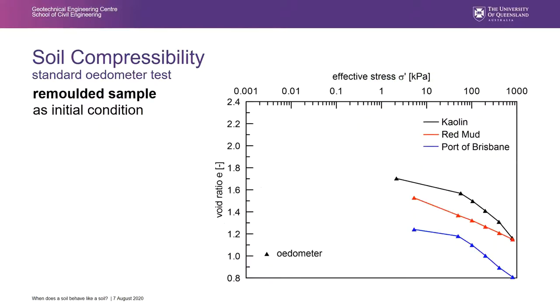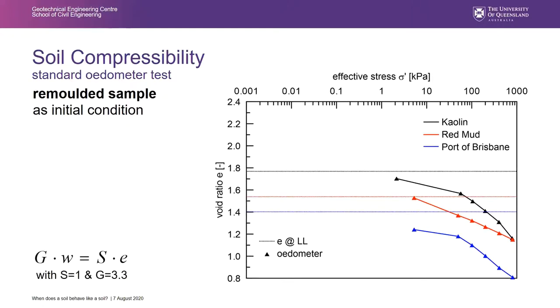So these are results now for different materials. And these materials have been remolded before. So we had in the black line kaolin, red mud, and Port of Brisbane dredged material. And these measurements were conducted with the oedometer test shown before. Now I introduce just the lines of the void ratio if we assume we have water content at the liquid limit. And you see that all the curves lie below that line.